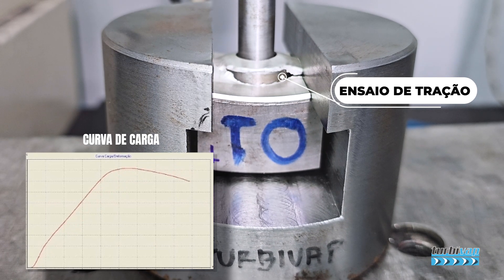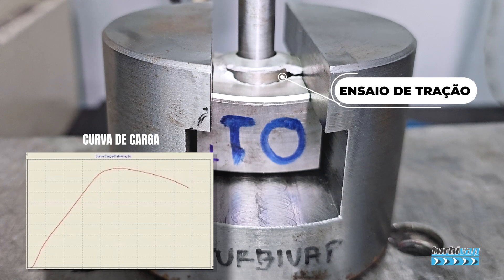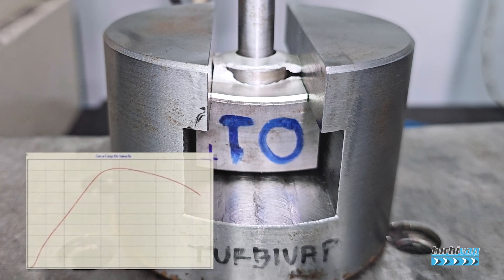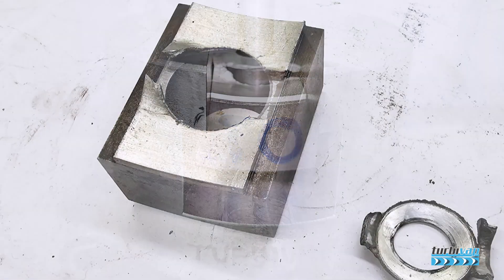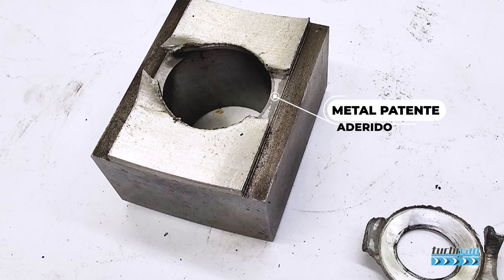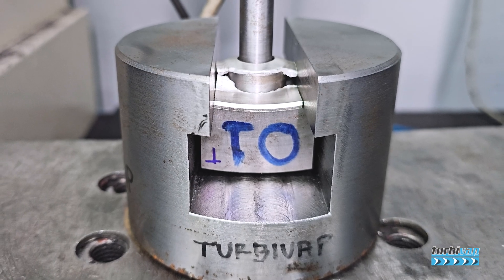It may not be so perceptible in the video, but in some cases, when we performed the traction and compression test here, we observed a small residue of metal patente remaining on the bearing base after shearing. This indicates that the adhesion at the bonding region between the two was superior, because it ended up segregating — separating one body from the other — while still maintaining metal patente deposited, obviously as residues, on the surface of the bearing base.